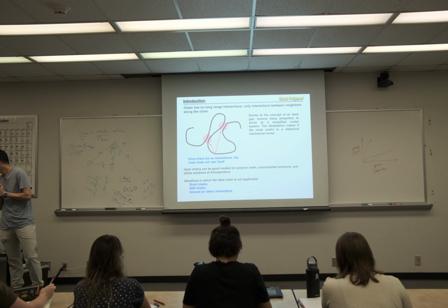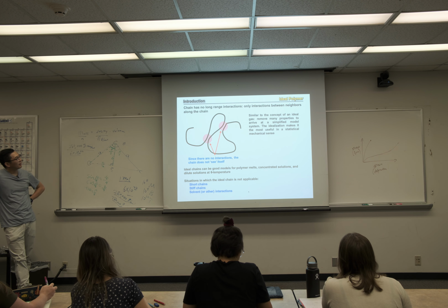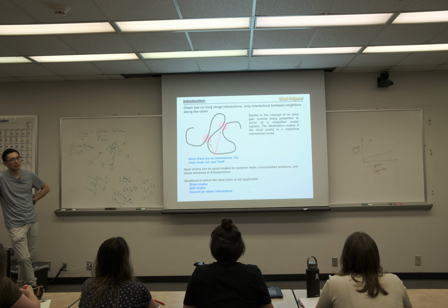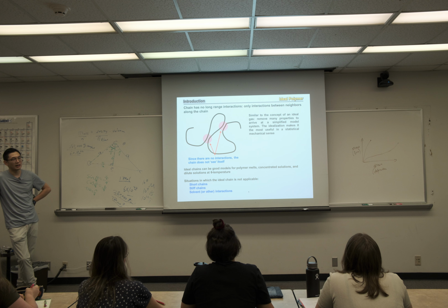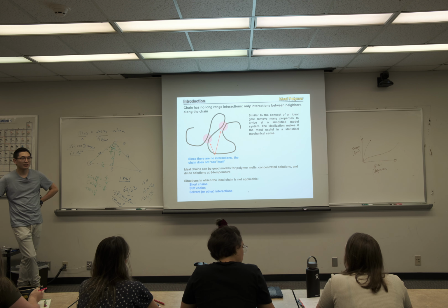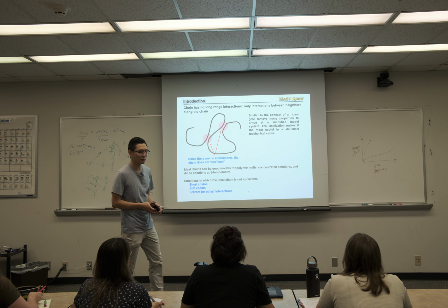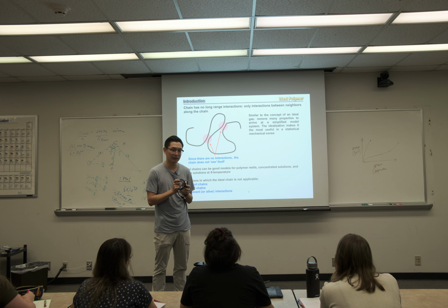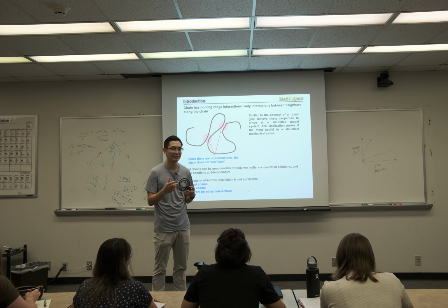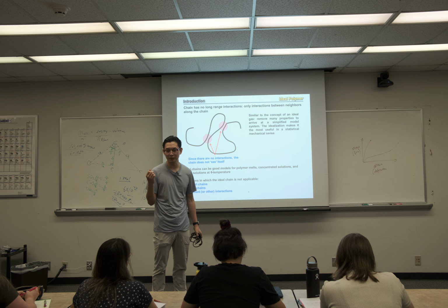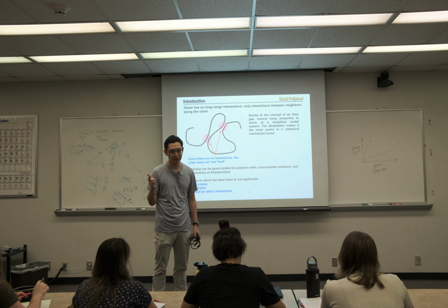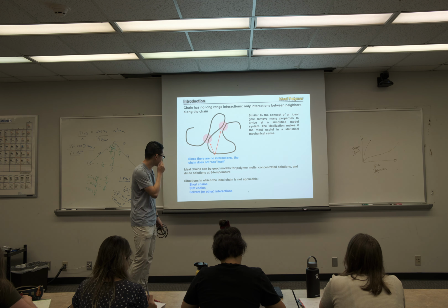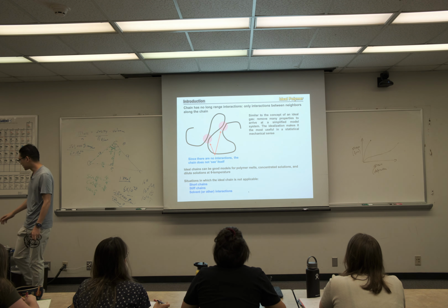Okay, now this we already talked about. Several ideal chain models. The chain has no long-range interactions in this case. Ideal chain just means it's idealized. It doesn't exist in the real world. One of the major differences is that you don't have something folding back onto itself, so no long-range interaction. Then we derived 3 different models: freely rotating chain, hindered rotation chain, and freely jointed chain. So we start with the simplest one. We're going to see the freely jointed chain in just a second.